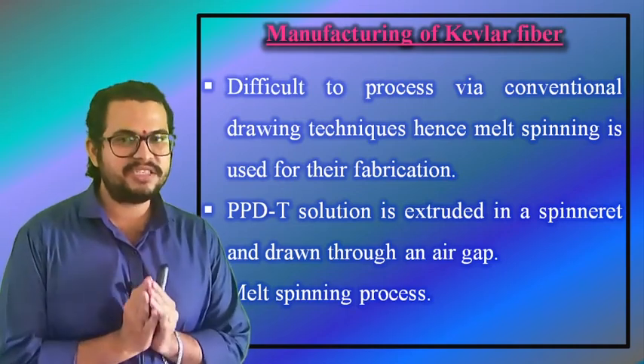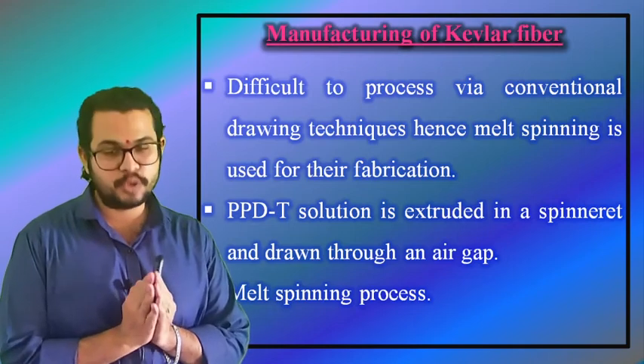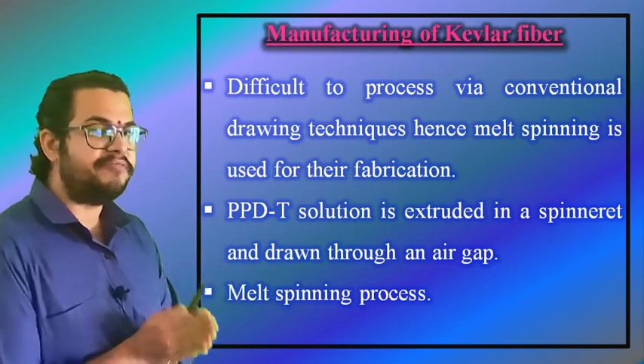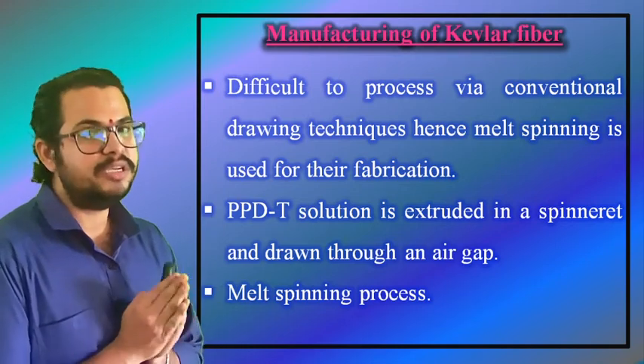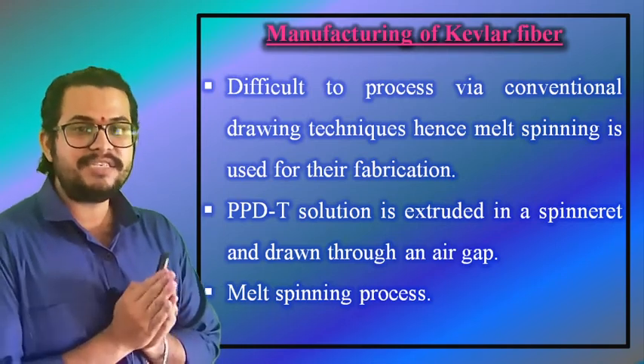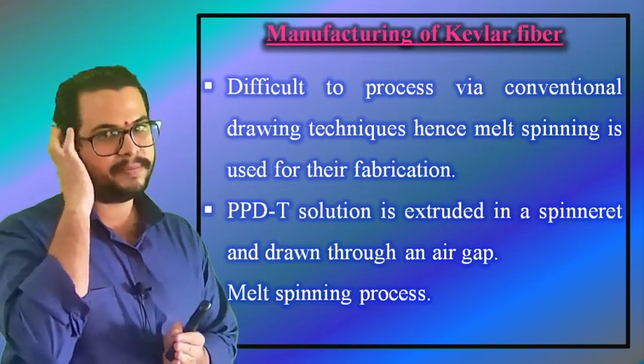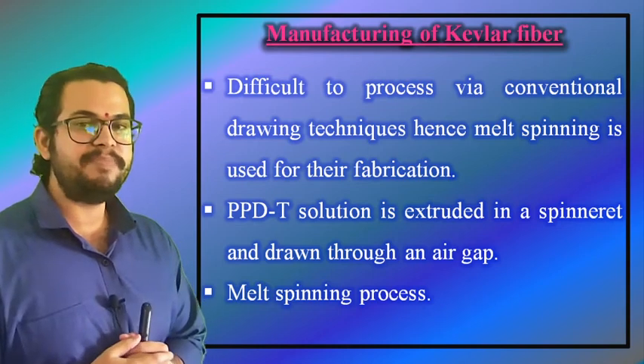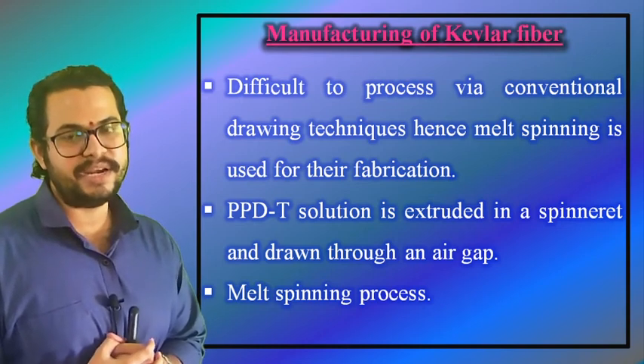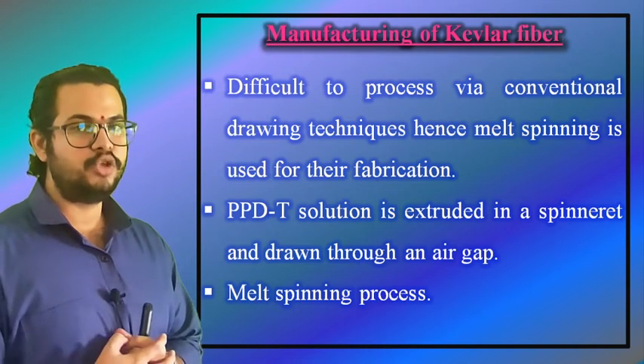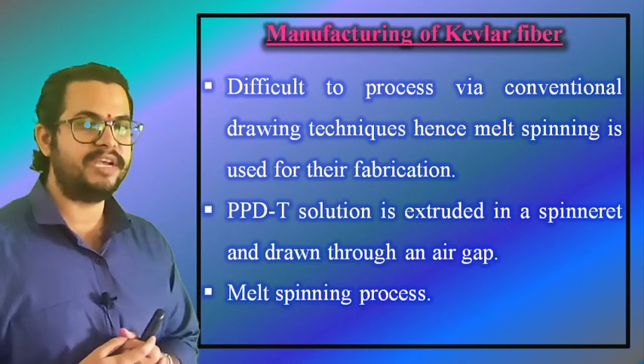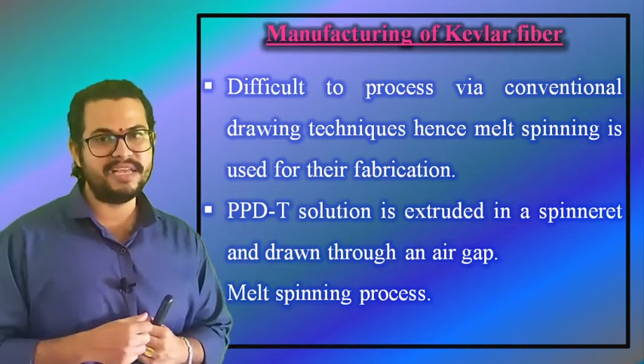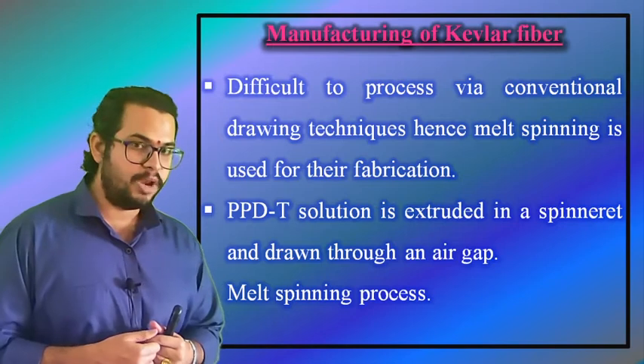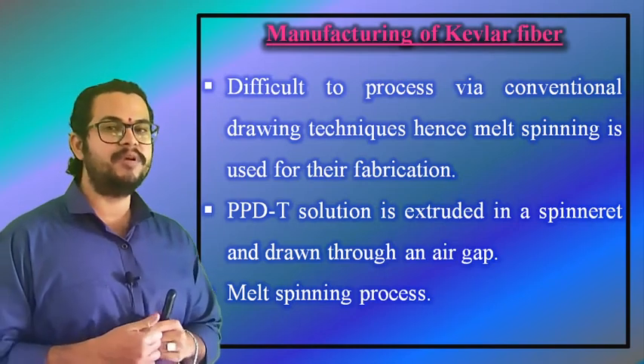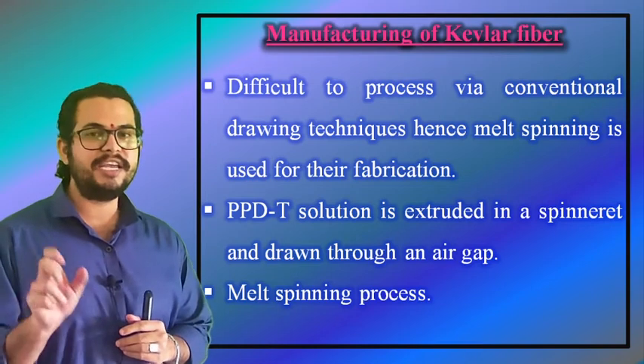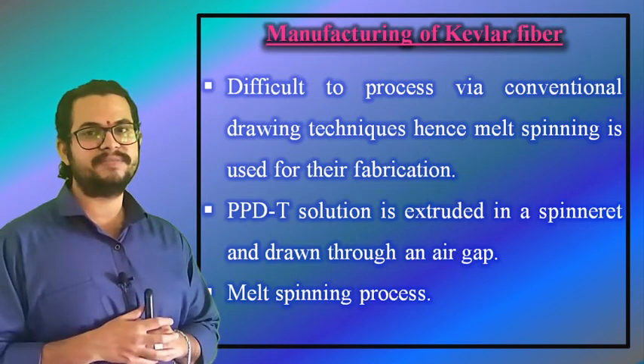Due to high glass transition temperature and poor solubility, these fibers are difficult to process via conventional drawing techniques. Hence, spinning is used for their fabrication. During this spinning, the PPTA solution is extruded in a spinneret and drawn through an air gap, resulting in the orientation of the liquid crystalline domains in the flow direction. The polymer chains also align in the fiber axis, resulting in a high degree of anisotropy in this direction.